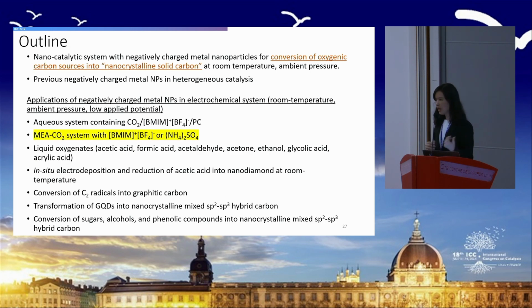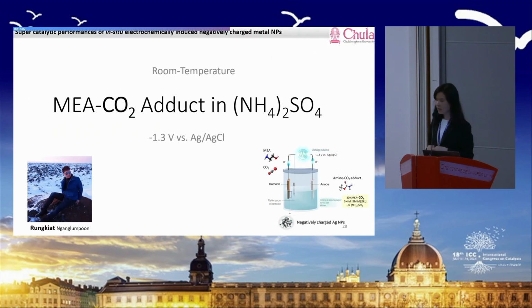That's when we work with the aqueous CO2 system, where we just have gaseous CO2 dissolved in our electrolyte. We're thinking that the mass transfer is probably not so good, and we want to have more CO2 in that system. So we try to modify our system a little bit. Now it's just a simple single compartment electrolysis cell where we have MEA to capture CO2. So CO2 will be chemisorbed in the form of MEA-COO minus, the carbamate species. And we can even replace the expensive ionic liquid. In the previous work we used BMIM BF4. Now we use ammonium sulfate salts. So now the carbon sources are just CO2, MEA, or the carbamate species.